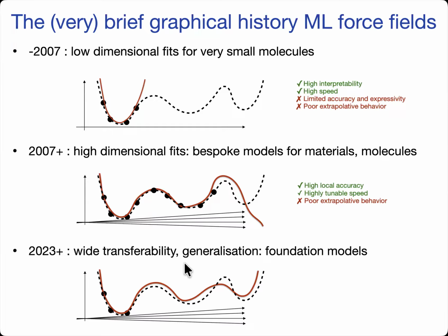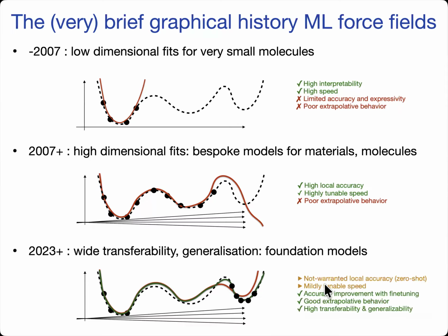And then the foundation models are where you train on a relatively small part of configuration space, and your model is quite reasonable everywhere. And we call them foundational models because if you want a simulation to be very accurate for a particular model, and you determine that out of the box it isn't, then you just take a little bit of new data there, not very much, and you fine tune. You adjust the model parameters a little bit. It takes a few hours on a GPU to do that, and then your model is very accurate there while retaining this sort of approximate accuracy everywhere else. So high accuracy with fine-tuning, still good extrapolation, and high transferability.